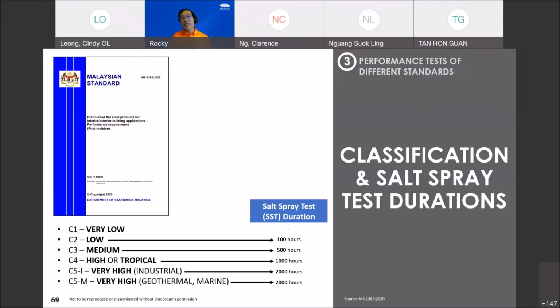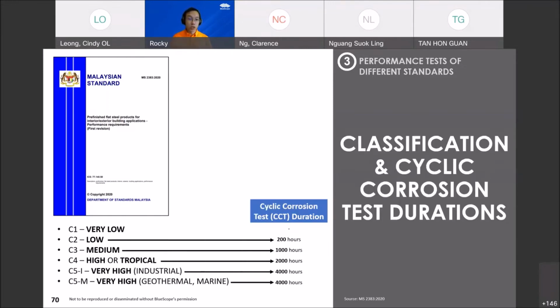But within the standard itself, there are some discrepancies as well. So over here, I'm showing you the salt spray durations, and I'm also showing you the cyclic corrosion resistance. Right over here, you can see C3, which is 1,000 hours, as opposed to salt spray of 500 hours. And then C5 originally was 2,000. Now cyclic corrosion is 4,000 hours.